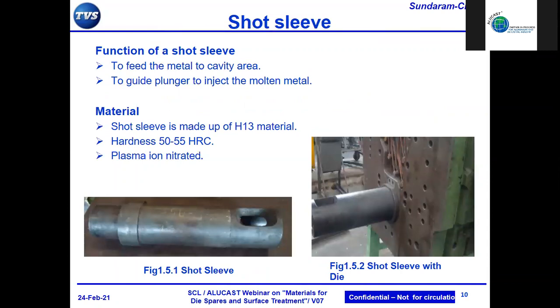Then we have the shot sleeve. Again, the shot sleeve has an interaction with the hot liquid metal, and then it needs to be highly erosion resistant, so higher hardness than the basic insert material. So hardness around 50 to 55 is normally done on this material. To attain this kind of hardness, we have plasma ion nitriding or any of the coatings. So this is where the coatings come into play, where you need to enhance the surface properties or surface modifications have to be done on the tool steel.